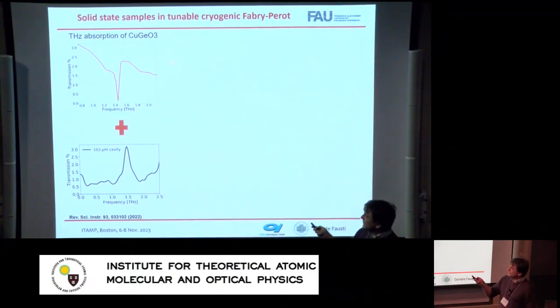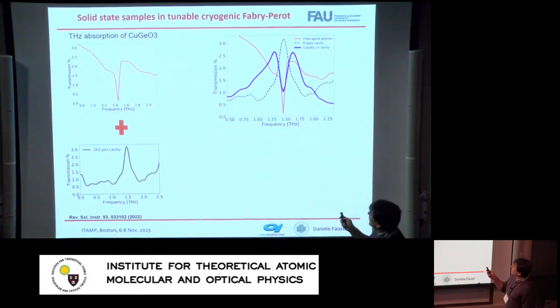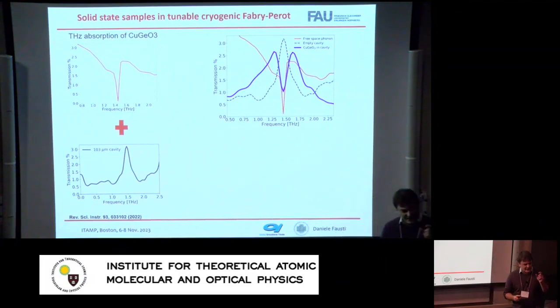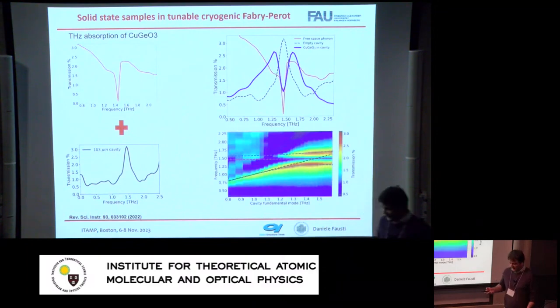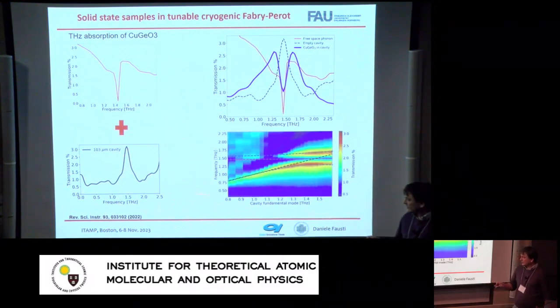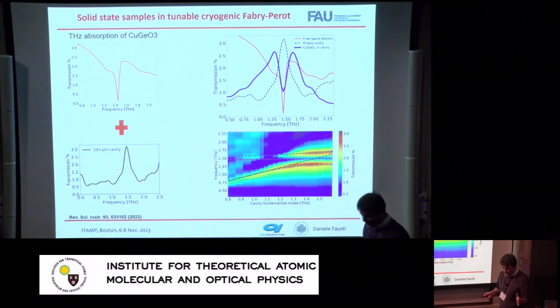So we chose a system to demonstrate that this is possible. We chose a system where we have a sharp phonon resonance, and we tuned a cavity in resonance with it, which we could tune across this phononic resonance, and we observe that we do have a large collective coupling, in the sense that we have a Rabi splitting which is larger than the phonon line width and than the cavity line width. Okay. I think that the merit of our approach is that now we can actually fully tune the cavity, and we can see the avoided crossing, and explore essentially the coupling as a function of the frequency of the cavity.